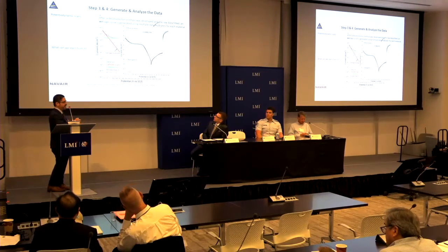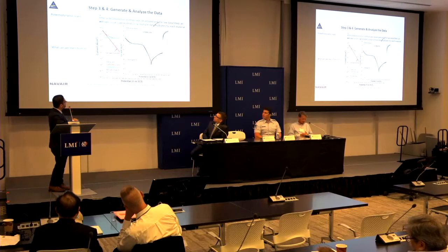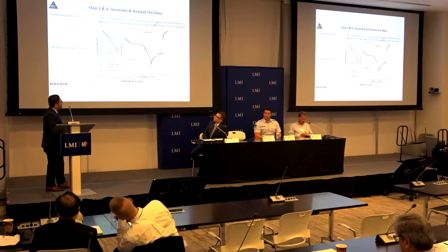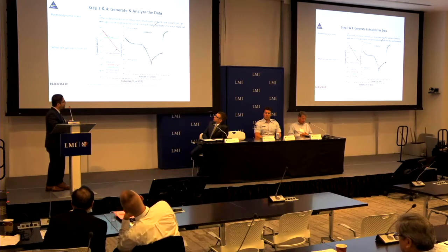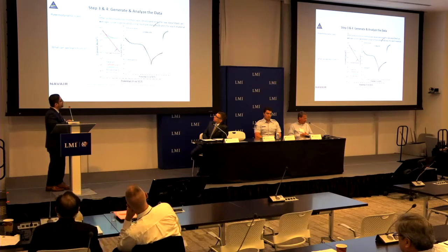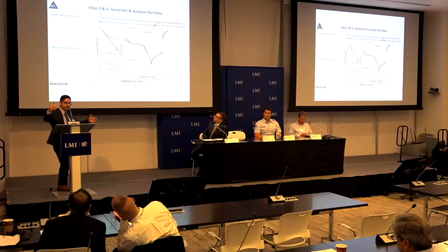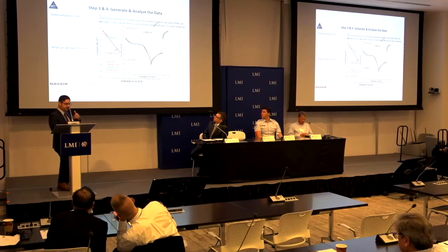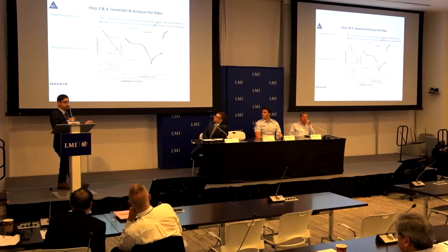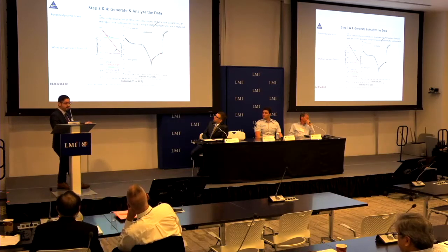Pitting is a type of damage that occurs in metals. It also tells you, when it acts as a cathode, how easily it can take electrons away from that metal, for example, from aluminum, right? You can extract a lot of that information. And after that, we developed a methodology also to analyze the data. So this is actually not the raw data. This is the fitted data. Basically, we take a bunch of data, average it, and then have this piece of data that you can modify whichever way you want and extract the values.